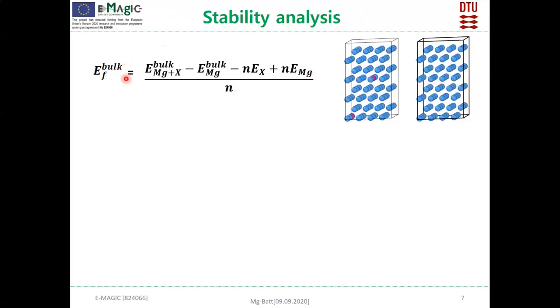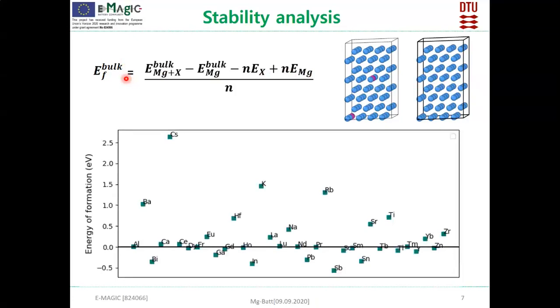And for an alloy to be stable, the bulk energy of formation should be negative. So you can see the results in this figure. The elements which show a negative value are mostly stable. So almost 20 elements are stable, and most of them are rare earths. And the elements which are not stable are mainly first and second group elements which have a bigger atomic radius. This may be the reason that they are not soluble. And the other elements like hafnium, titanium, and zirconium are known to be less soluble. So this agrees with our study.